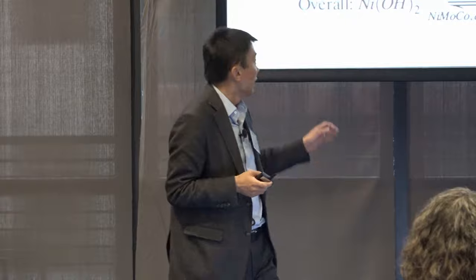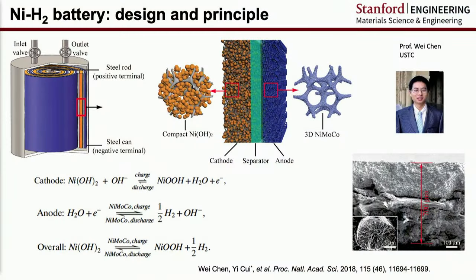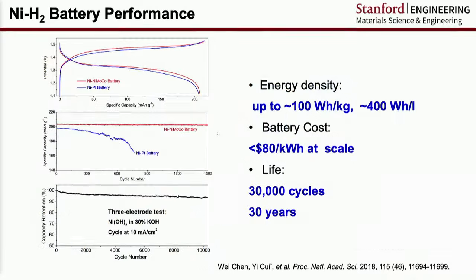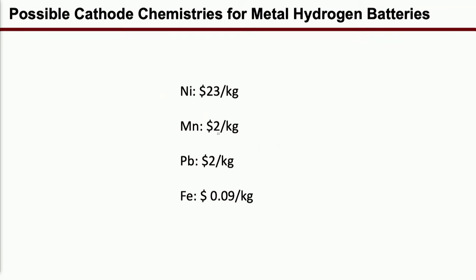So we replaced platinum and invented this new catalyst, nickel molybdenum cobalt. It works really well, and the cost is reduced by 10,000 times, so now it becomes civilian use. We show this has very long life, so I won't bother you with all the data. Not only that, nickel is still not the lowest cost material. If you want to go to scale, gigaton, 100 terawatt hour, we need lower cost, more abundant materials.